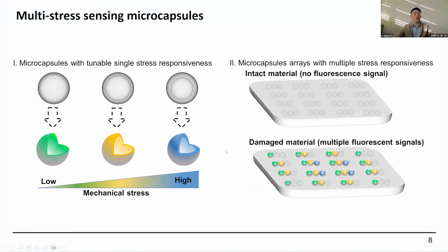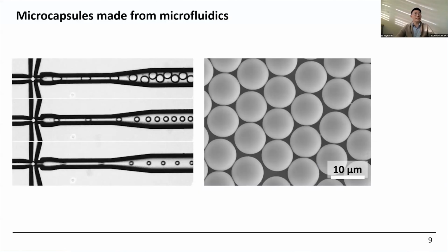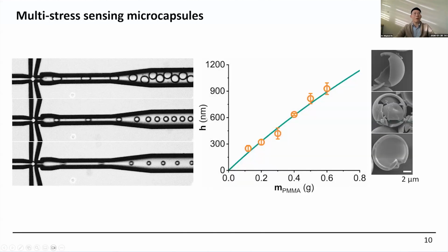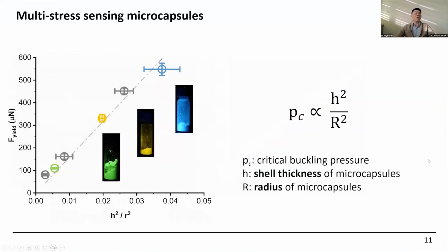To do that, first we need to synthesize microcapsules with different shell thickness and diameter, and we use microfluidics because microfluidics is a very precise tool to make droplets with precise diameters. As I show here, we can nicely tune our microcapsule diameters. Also, we can make them very monodisperse. And by controlling the polymer we use in the microfluidic synthesis, we can also further tune the shell thickness of the microcapsules.